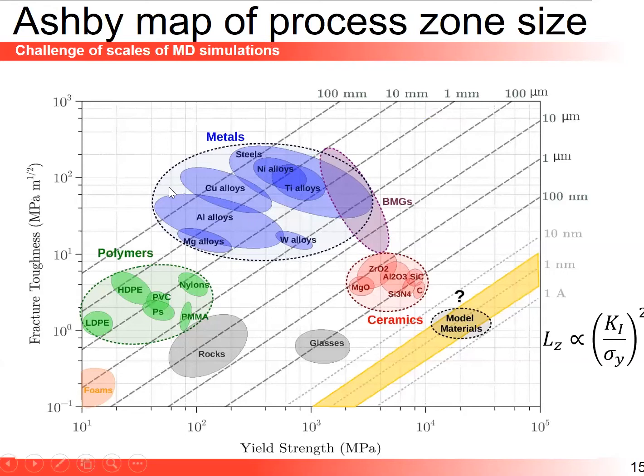So here, this is an Ashby map. You have different groups of material. Metals are here, you've got rocks here, and this is fracture toughness as a function of yield strength. And an estimation of a process zone size at a crack tip, the zone where you have nonlinear dissipative mechanisms occurring, is the ratio of fracture toughness to the yield strength, squared, and this is a large quantity. And I'm reporting values here with those oblique dashed lines. So for metals, it's typically millimeter sizes. For rocks, it's typically micrometers.